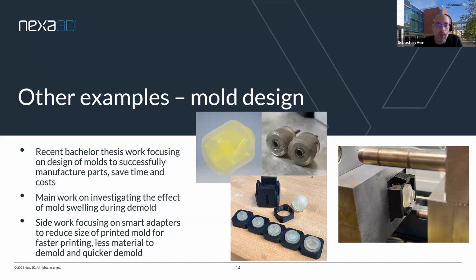We also, in the same step, created adapters where we adjusted the molds. So we have this base mold, as you can see on the right side, the metal part, but then we have inserts that are also kind of adapters where we can easily put these smaller molds. So for each part, we designed also this black base mold, which is a typical resin for DLP or SLA printing, which can be reused. Well, they didn't break, so I would say you can reuse them indefinitely, but definitely a lot of times. And then when you just place in these small parts that you have to dissolve, you actually do a lot of saving time and money in the process.